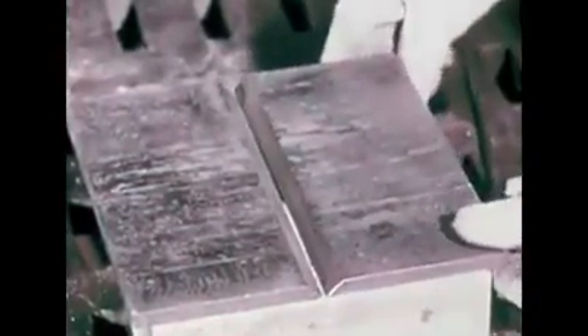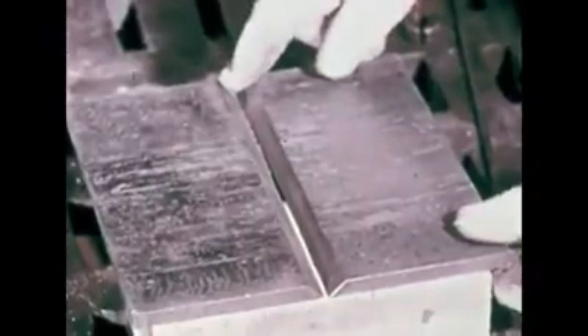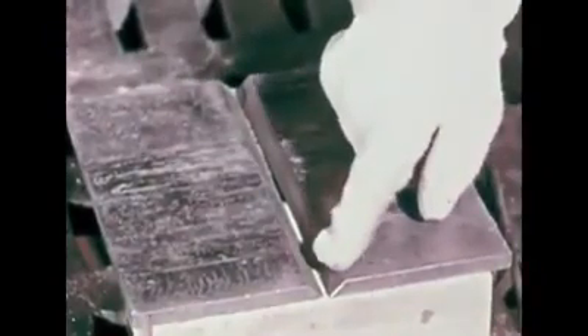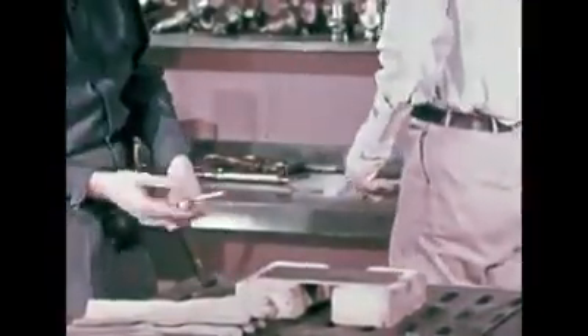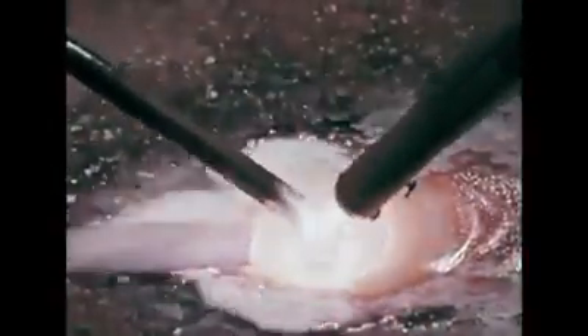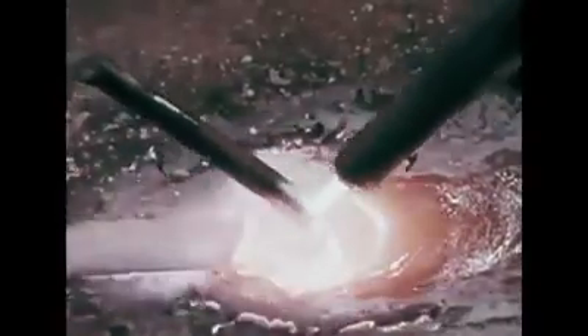Let's review the important points we have covered. Always space plates to be welded. 1/16 inch at the right, wider at the left, depending on plate thickness. Use a larger size blowpipe tip when welding heavier thicknesses, and also use a larger size welding rod. Adjust the blowpipe flame to neutral. On the first pass, melt down the sides of the V. Add welding rod metal after the sides and bottom are molten to form the weld puddle. Keep the puddle moving.